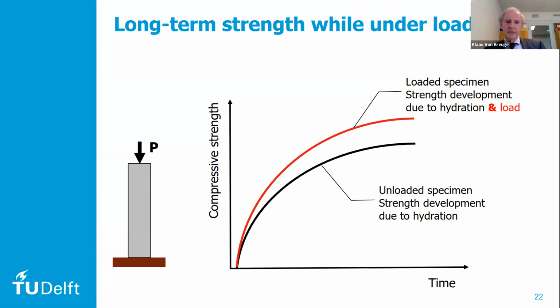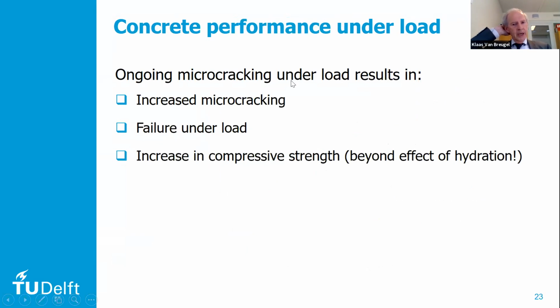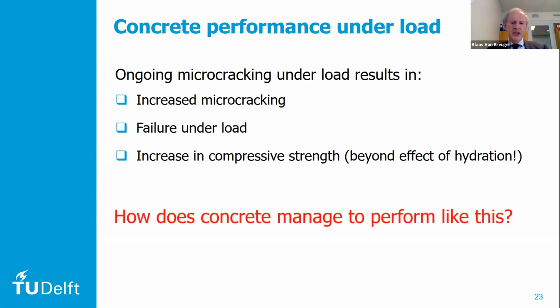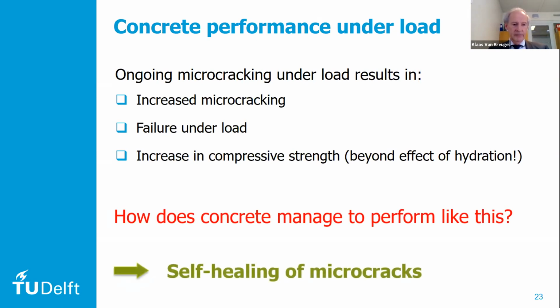And on the other hand, you see an increase in strength. And that's very contradictory, that a sample that would increase in strength would finally fail. That's a little bit strange, isn't it? So we see that the ongoing microcracking results in failure under load, or an increase of compressive strength. An increase of the compressive strength beyond the strength of a sample that was not loaded. So how does concrete manage to perform like this? Well, it is actually self-healing that does that.